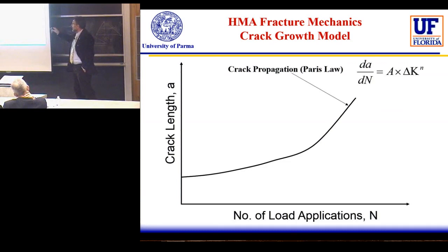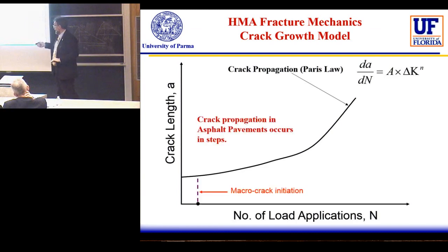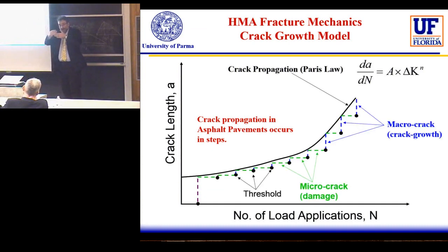Again, looking at the traditional approach of crack propagation, that is the Paris law, we can have an interpretation of this phenomenon from the point of view of HMA fracture mechanics, considering a step by step propagation in the material. So if you have your material and somewhere in the material the threshold is reached, you have the macro crack initiation. From there some micro cracks start, and as soon as we reach the different threshold, we have a coalescence of the cracks that develops the crack in the material.